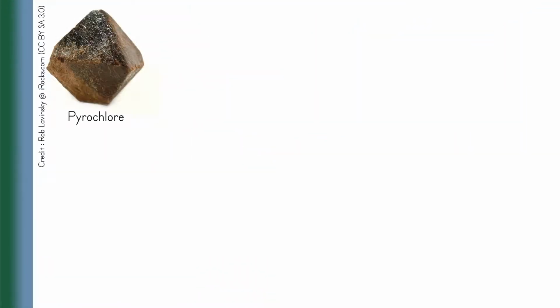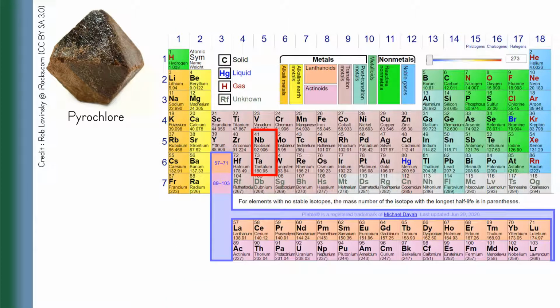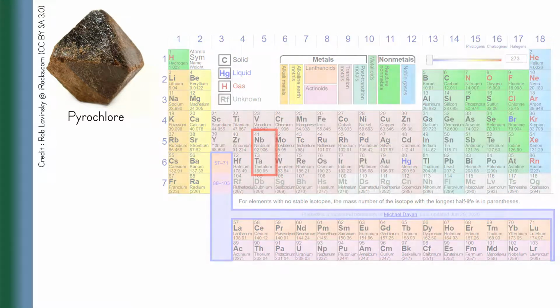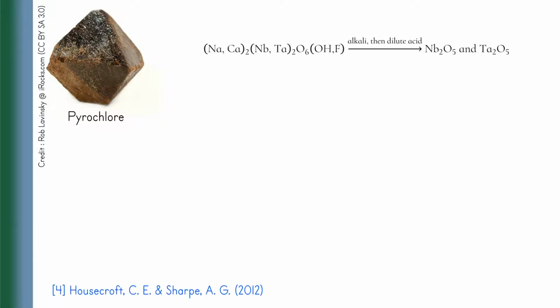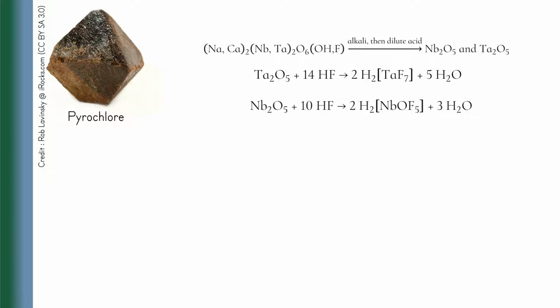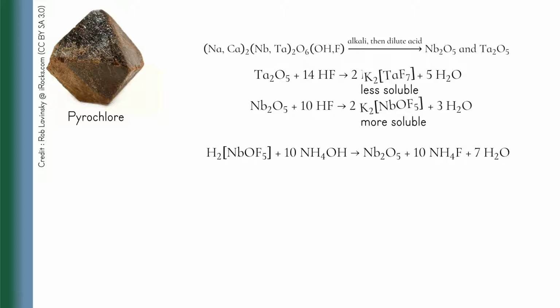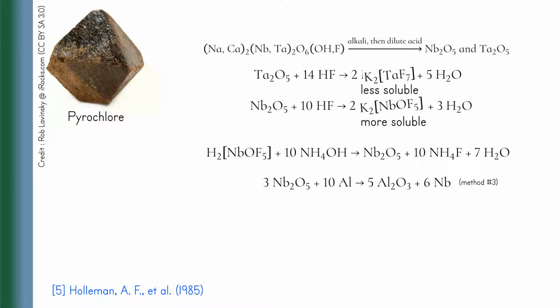For pyrochlore, the main problem is that it's mixed with its periodic table neighbor downstairs, tantalum. Again, just like with molybdenum and tungsten, same column, same chemistry. After treating the ore with alkali and dilute acid, a mixture of niobium pentoxide and tantalum pentoxide is made. These oxides are reacted with hydrofluoric acid to make these fluoride complexes. And because the potassium salts of this metal fluoride have different solubility in water, they can be separated. With the tantalum out of the way, the potassium niobium fluoride can be converted to niobium pentoxide form using ammonia. The niobium pentoxide can be reacted with aluminum again, as usual, to make its metal form. Well, that is one way of making niobium.